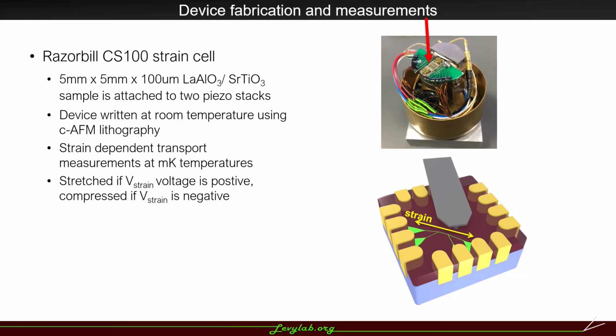When we apply a positive V strain voltage to the strain cell, the sample will be under uniaxial tensile strain. When we apply a negative V strain voltage, the sample will be uniaxially compressed. We calculate the actual strain from displacement of the sample, which is measured by capacitance change.